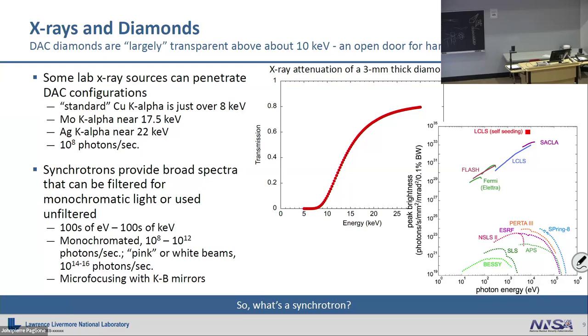Most work at a synchrotron, I would say, is monochromated in the beam. That means you take all of this and you just pick a delta function somewhere, and those are the X-rays you're going to take out of there. And so when you're monochromated, this is maybe an idea of the flux that you get, 10 to the 8 to 10 to the 12. Some beam lines are a little more, a little less, depending on what they do.